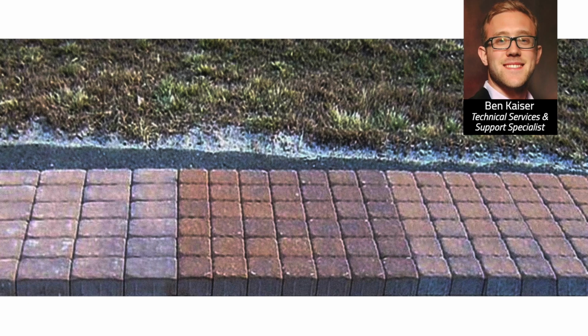The last set on the far right was the same system as the set in the middle, but the exhaust vents stayed open throughout the whole cycle, allowing moist, warm air to escape. So there was not sufficient humidity in the bay for optimized curing to occur. It's very tempting to think that as long as the products are placed in the kiln, you have done your bit and everything will be fine. As always, the devil is in the details. Simple actions like closing a door can make a big difference.